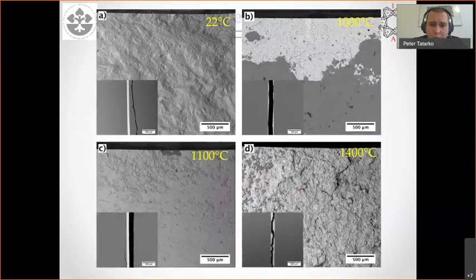If you look very briefly at a few images of fracture surfaces, you can see that at room temperature, the sample failed outside the joining. Here you see the joining interlayer, and the sample failed outside the joining area. With increasing temperature, here you see 1000, 1100, 1400, the interface or the filler played a more important role, and especially at a very high temperature, the filler was the weakest part of the joint.